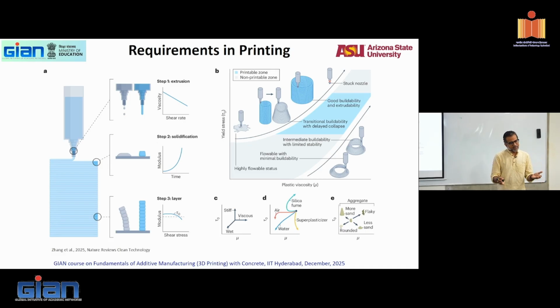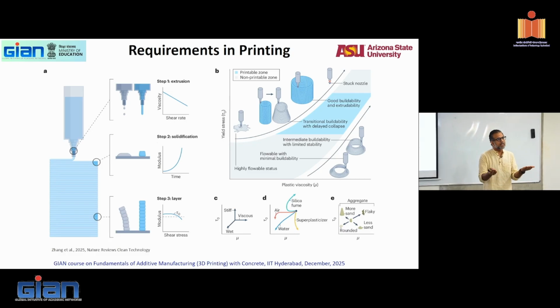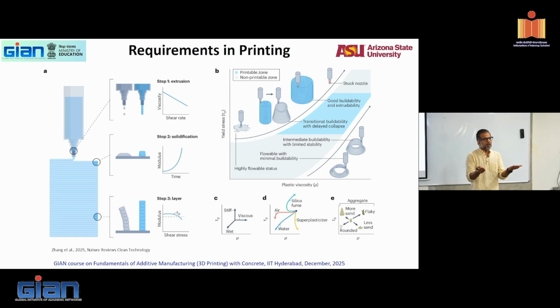Now, if I have an intermediate buildability, yes, I have my yield stress and plastic viscosity controlled in such a way that I can start building it up. But then once it gets to a certain height, the yield stress is not high enough to hold the layers that are below. Right? There is not enough stiffness to hold the layers below. Intermediate buildability. What do I want then? I want it to go higher yield stress. Now, I can increase the yield stress higher and I can increase buildability as much as possible.